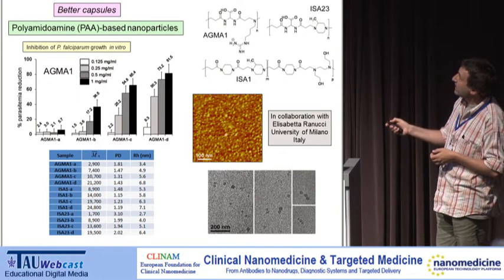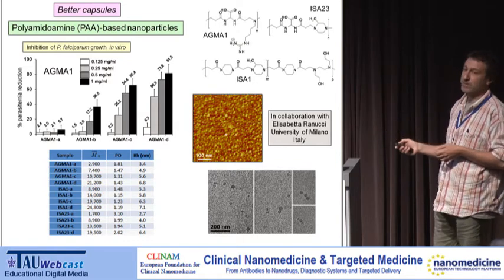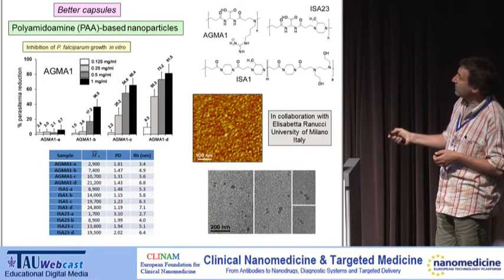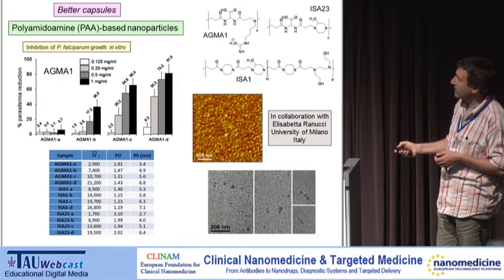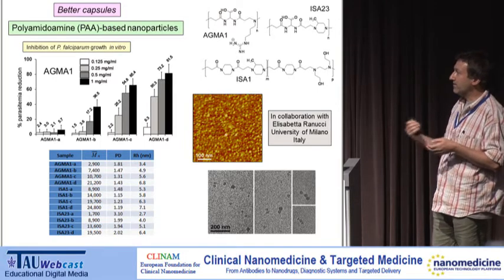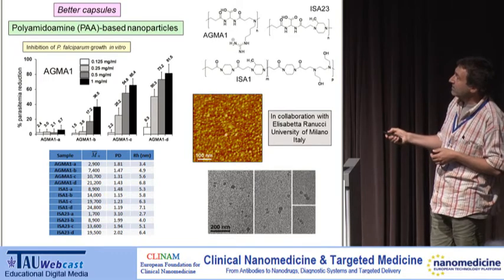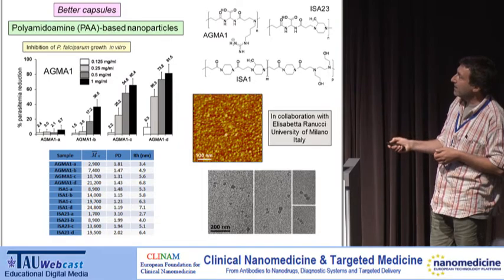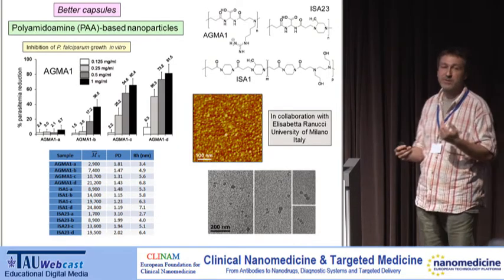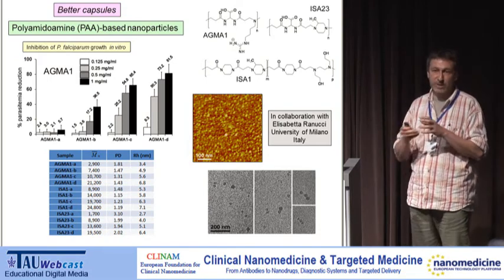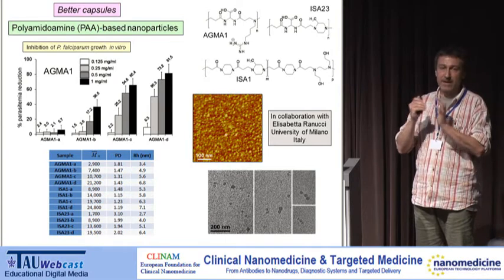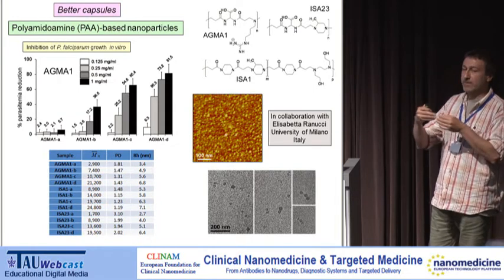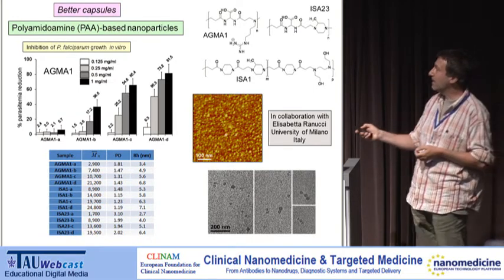Particularly, we have been using polyamidoamine-derived nanoparticles. Polyamidoamines are this type of polymer, and we started testing three of them. They form small nanoparticles of about 20–40 nanometers across. The first interesting finding was that some polyamidoamine nanoparticles, like AGMA1, have an intrinsic antimalarial activity. We decided to continue in this direction because we could potentially have a nanoparticle with antimalarial activity in itself, and if we encapsulate antimalarial drugs and add a targeting molecule, we could achieve a synergistic effect.